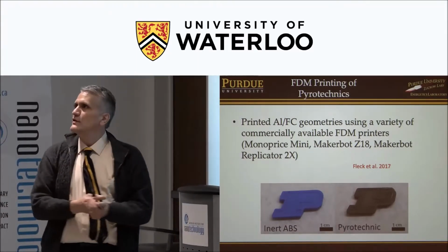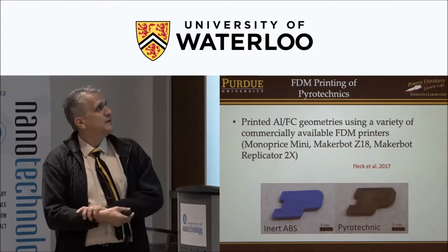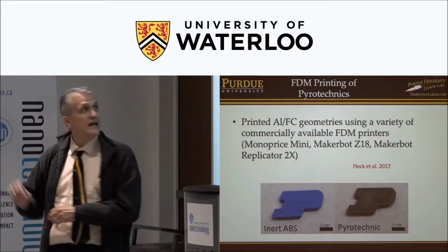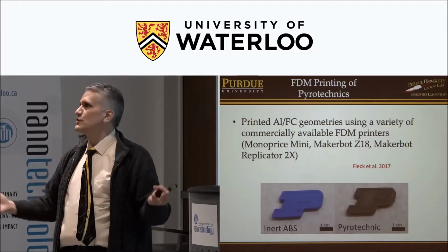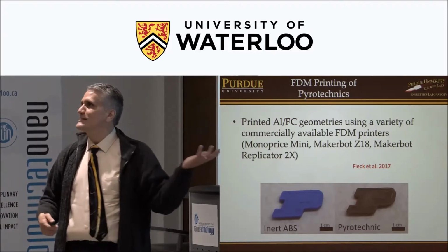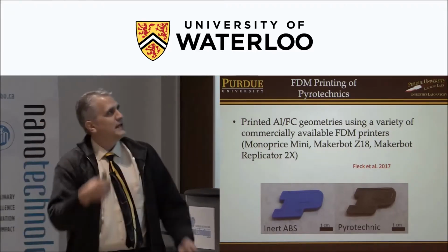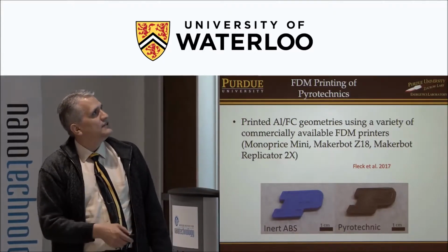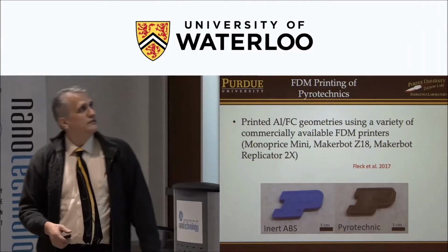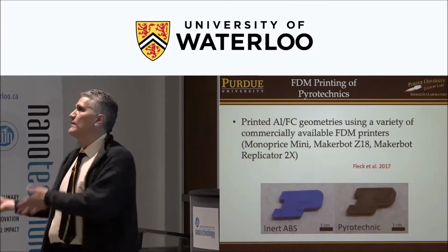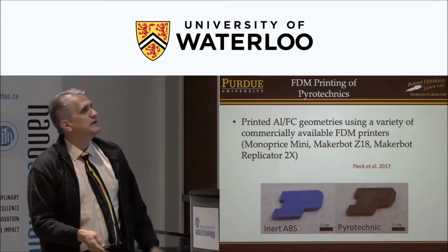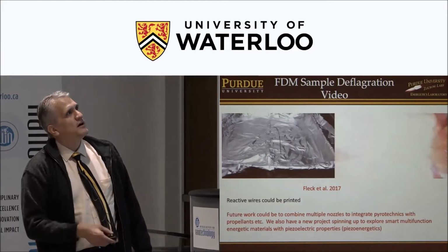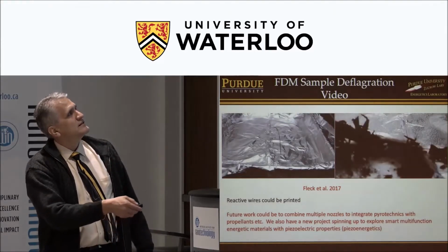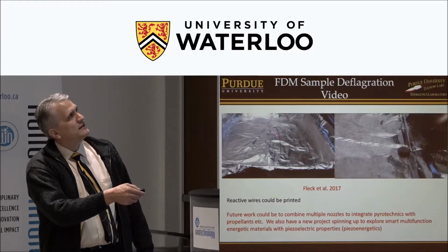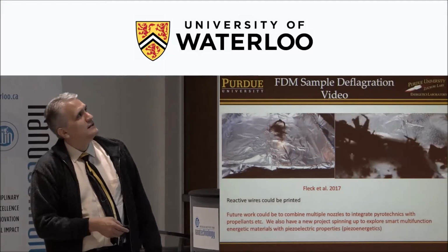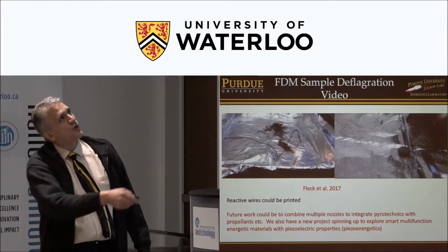So first of all, we have to mix the aluminum with the PVDF, and we have several methods of doing that. And we make little pellets, and then we put those pellets in a filament maker. That's just a commercial filament maker. You can buy those actually to recycle your printed parts if you want, and make new filament to print in your FDM printer. But we use it to make a novel filament. And then we can take that filament, put it into a MakerBot or whatever, and print up reactive parts. This is a little printed puck. It shows that it's reactive. And this is actually just a filament here that you ignite. It's producing a lot of carbonaceous and also aluminum fluoride products.